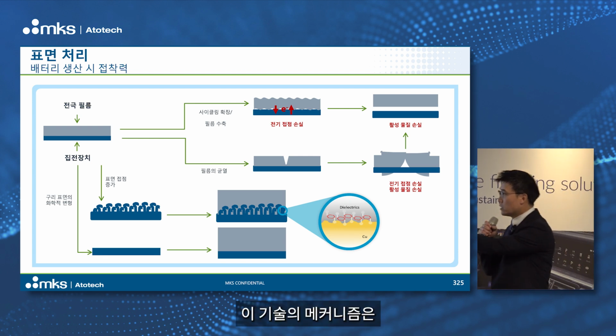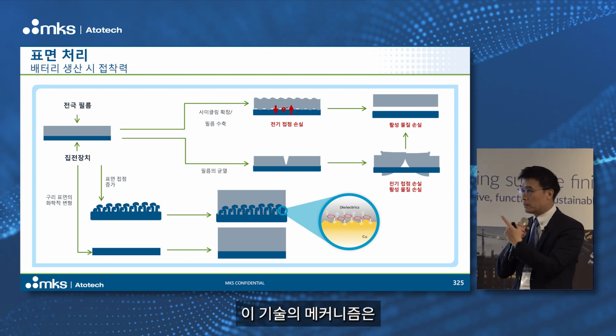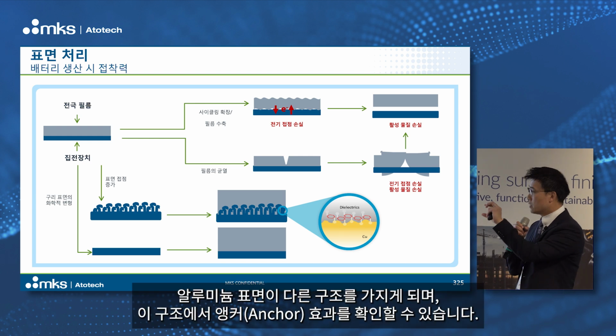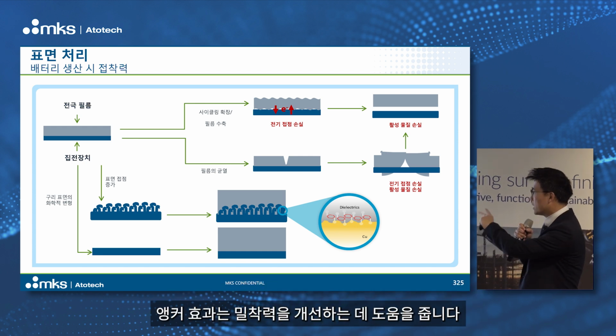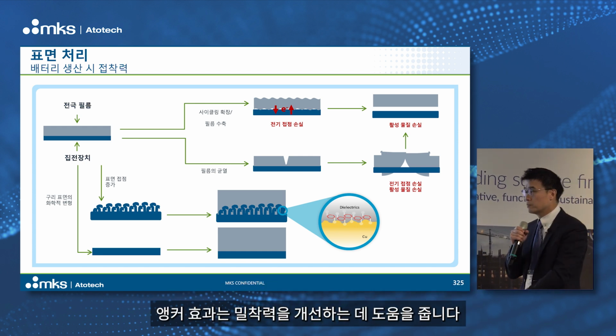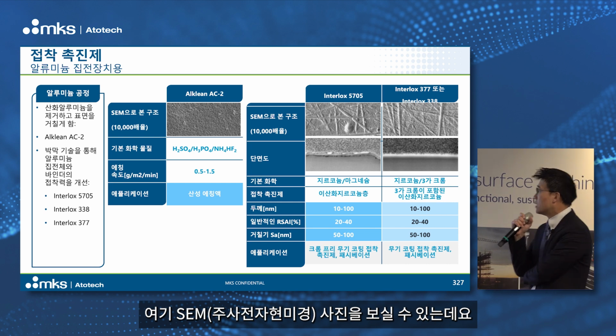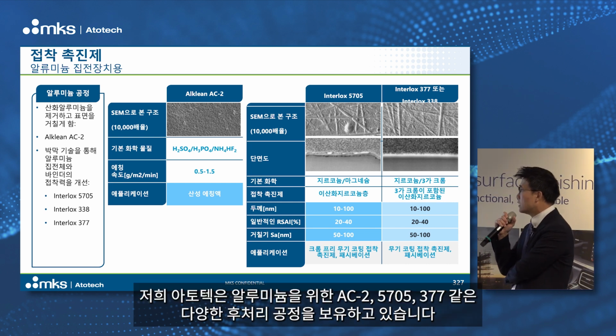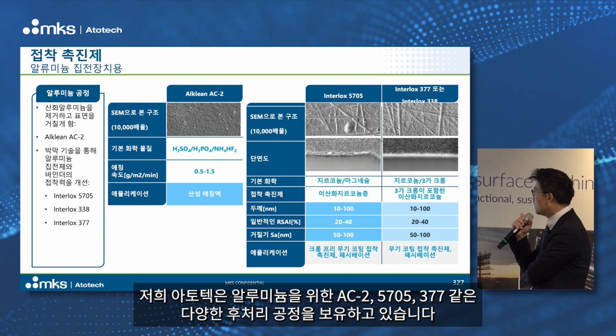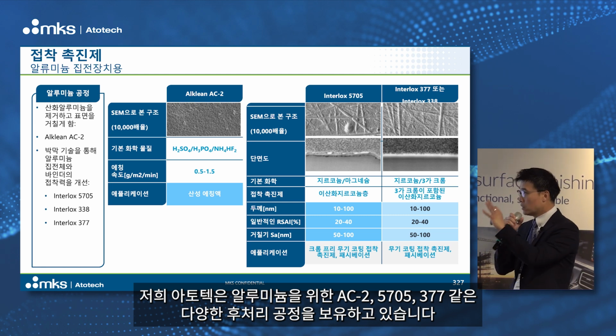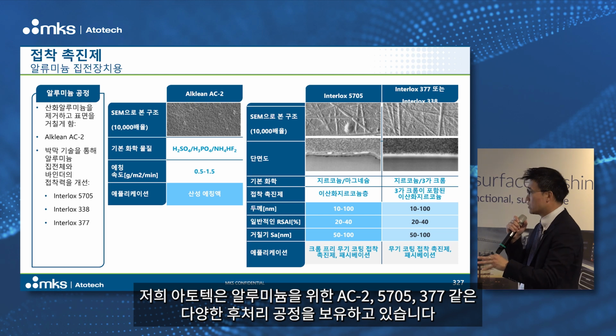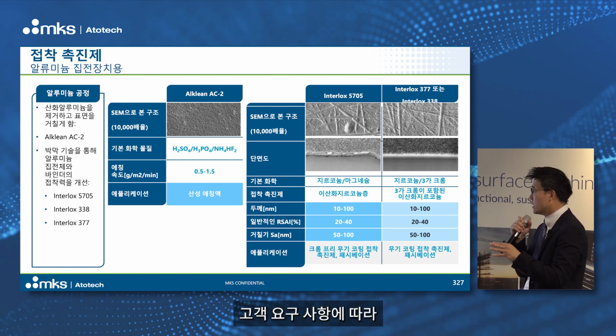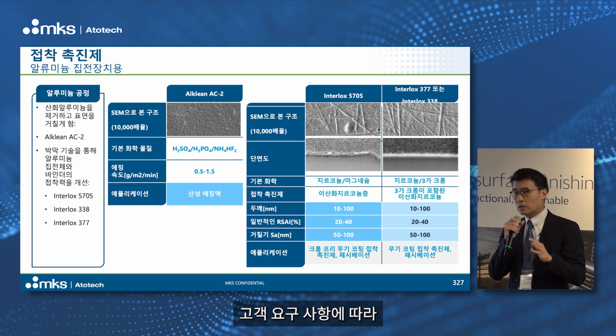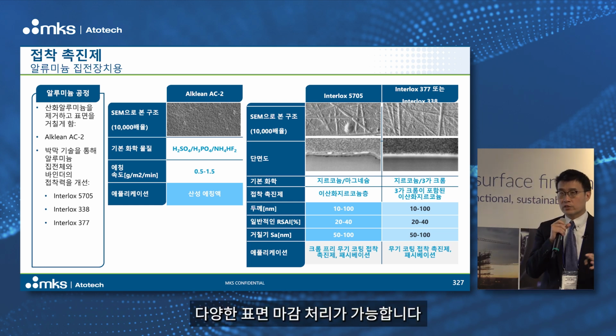So our solution is really to have a surface treatment which could enhance the adhesion of the surface. The mechanism is that with our surface treatment, the surface of the aluminum has a different structure, and you can see all these anchors, and this helps improve adhesion. You can see the SEM picture here. We have different processes like AC2, 5705, 377, different post-treatment processes for aluminum application, and according to the customer requirement, we can have different surface finishing.